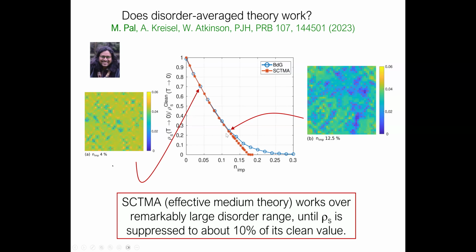And you see the result here, which is that you start with a clean system, you calculate the superfluid density in a progressively larger number of impurities, and eventually the two results for the disorder average theory and the simulation, they break ranks. But it doesn't happen until the superfluid density is about 10% of its clean value. And so we consider this to be a pretty big success for using this disorder average theory or dirty d-wave theory to describe a lot of the dome. It doesn't tell you, of course, about the very end of the transition, and I'll come back to that in a second.